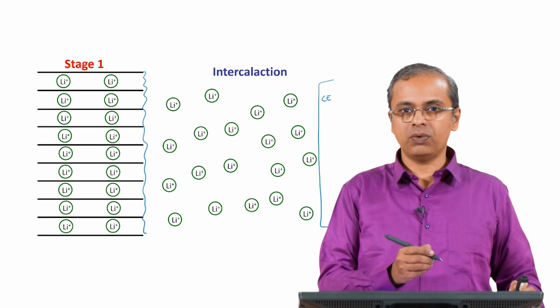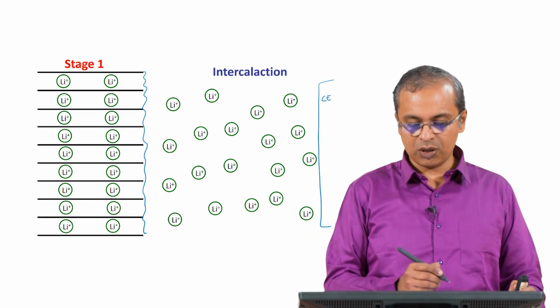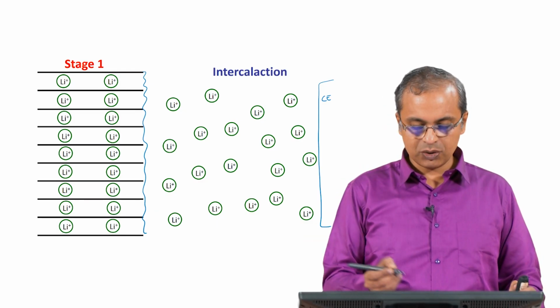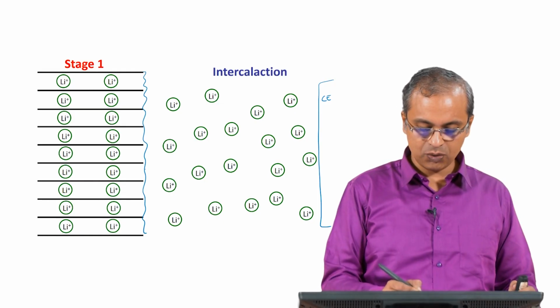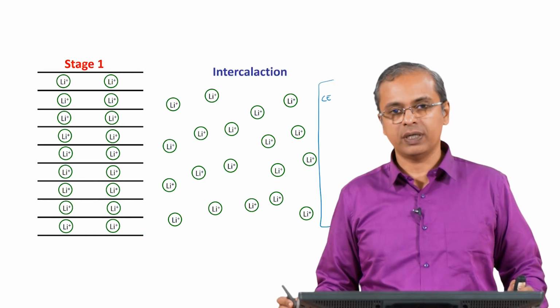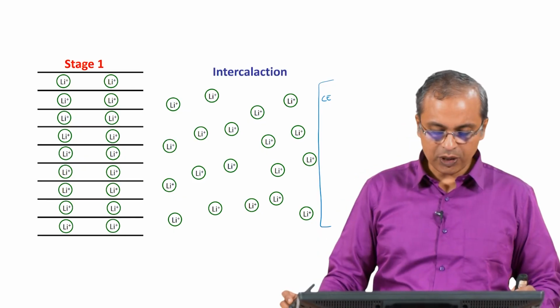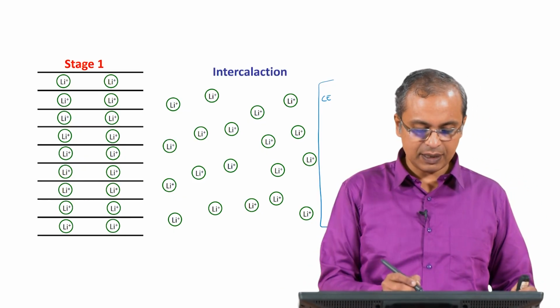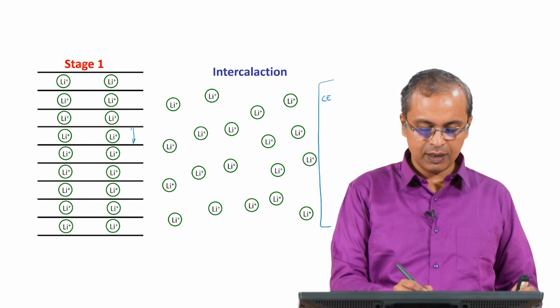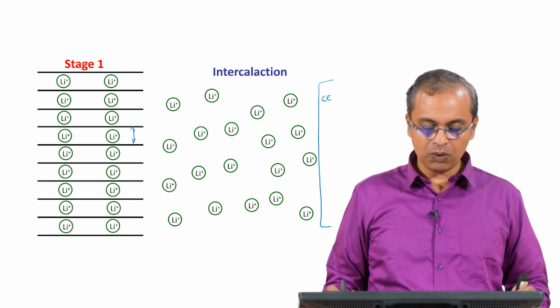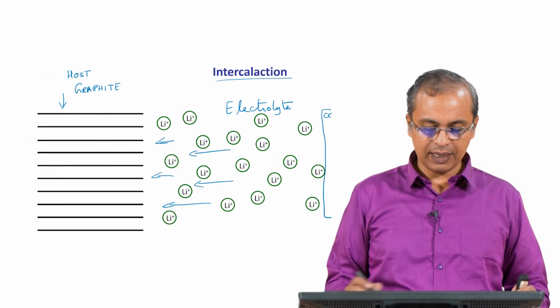This idea of dendritic growth is not happening, it is not growing such that you will have a short circuit. So, all that is not happening. So, this safety issue which was there with the lithium metal is no longer there. Okay. I will also point out that you can see here that the spacing has changed. If you compare this spacing here, it is significantly higher than the original spacing between the graphene layers, which is this.